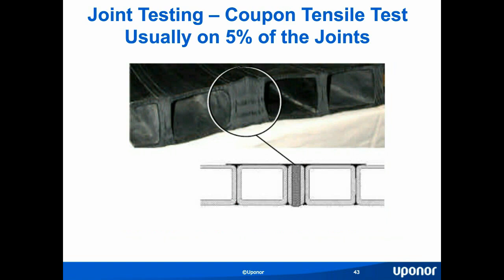Another joint test is to simply remove a coupon. And as you can see here from before, we take a sample from this weld. This is our internal weld that we have made in the past. And we take a coupon out, generally speaking, 2 inches wide and 12 inches long. And we take that and overnight it to our lab to do a tensile test on it. And it will break, but it can't break at 15 MPa or less, or it's not considered successful. And it can't break at the weld because we state that the joint is stronger than the pipe itself. And we can state that because there's more material in the weld than there is in the actual factory welds. So we can't have a break at our field weld. If there is, then obviously we have to take some corrective action.